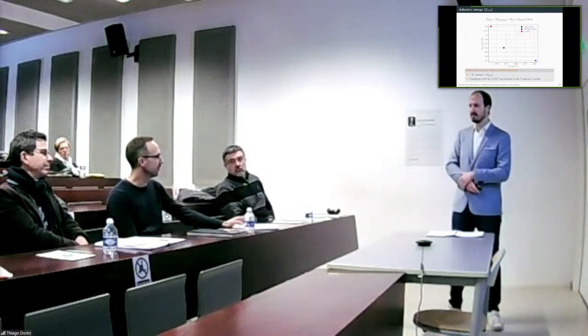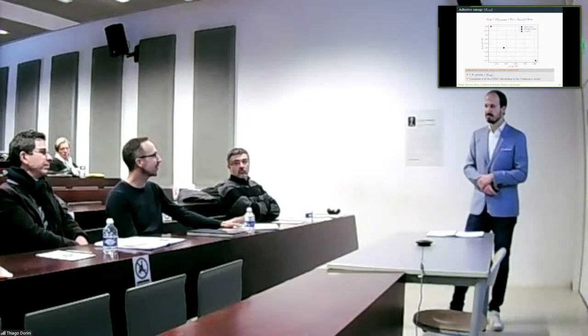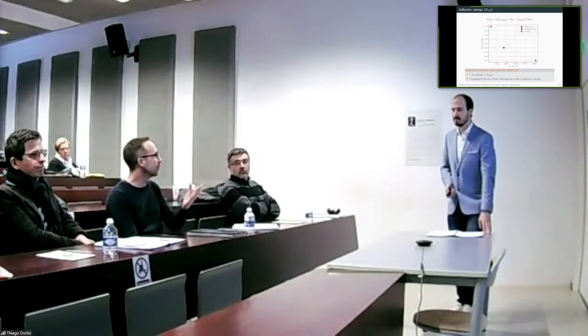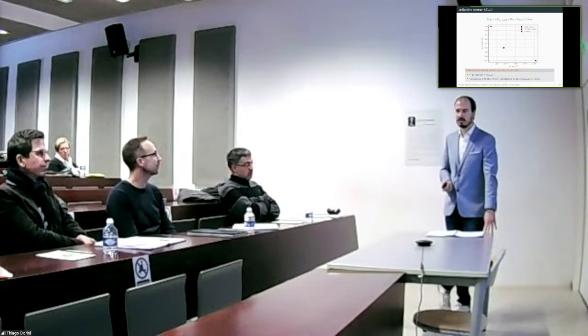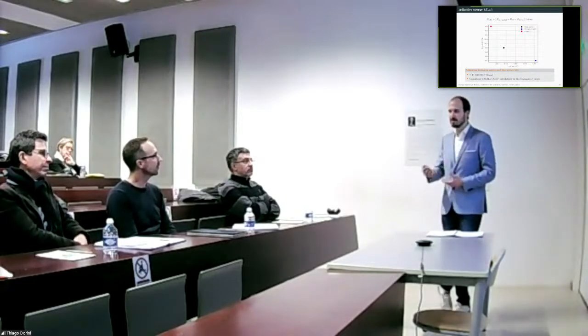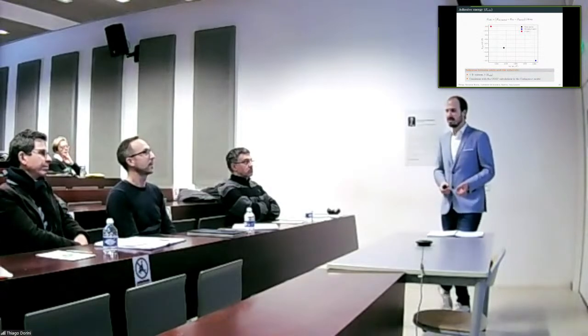Then I would have suggested that you include this decay of the structure also in the thesis, because this is then maybe the most obvious thing where you see that this is a wrong structure. Yeah, you're right. The low adhesion energy comes just from the low density of the material that you have. Yes, you're right. Yeah, I think, as you said, the adhesion energy might be one parameter for the stabilization, but it's not enough to say if this is actually more stable than the other.